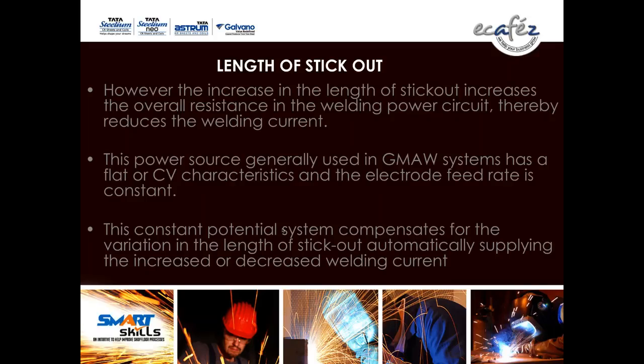The power source generally used in GMAW system will be flat or CV type characteristics. As I said earlier, for MMAW, the power source should be CC type. For MIG process, it should be CV type characteristics. The electrode feed rate is constant. With this constant potential system, it compensates for the variation of the length of stick out automatically, supplying the increased or decreased welding current.